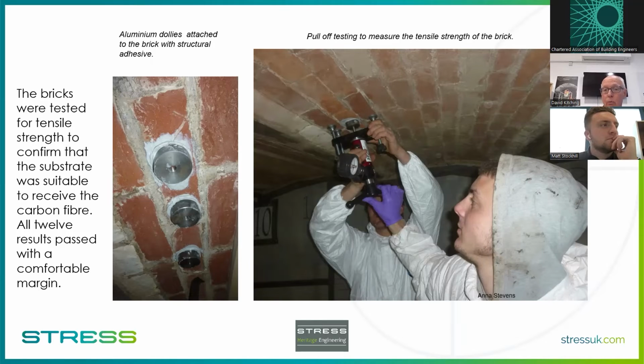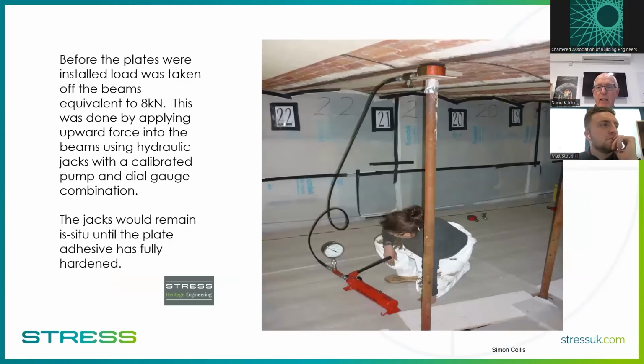In this case, in brickwork, even though we were really expecting something lower, we got nothing lower than about 2.5 newtons per millimetre squared, which is well in excess of what we need. So that was very reassuring.